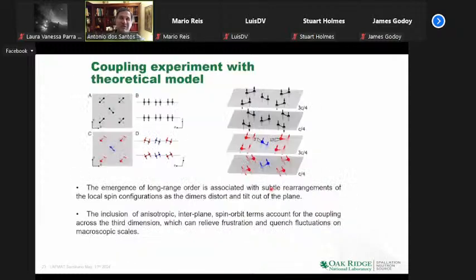Now, unfortunately, or fortunately, we had the powder data, and that allowed the solution and refinement of the structure. What we found is that we left the Shastry-Sutherland approximation: we bent the dimers out of plane, and the model basically doesn't apply. So we are truly seeing an antiferromagnetic order, not because J over J prime was changed, but because we intrinsically changed the structure with pressure. And this is something we wouldn't be able to do without neutrons.